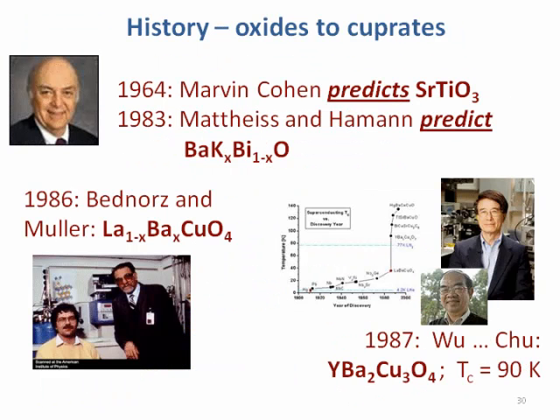So then, just giving the history again, these are the ones that some people think were actually predicted. These guys don't like this when I say it, but I don't think they're really predicted. So Marvin Cohen told me otherwise, but I still give him credit, which is, he wrote his PhD thesis that a semiconductor called strontium titanate, and it's actually more than a semiconductor, it's a hard insulator. Okay, it's a real insulator, like sand, okay? He predicted that under pressure, for a variety of reasons, this thing should superconduct. It turns out under pressure, and if you dope it, it does superconduct. His reasons were wrong, but he still claims that as a hit.